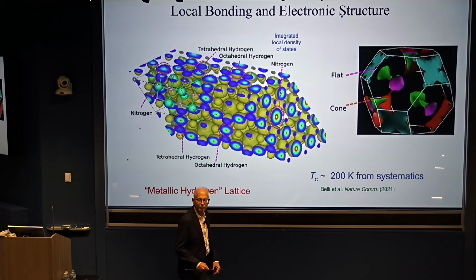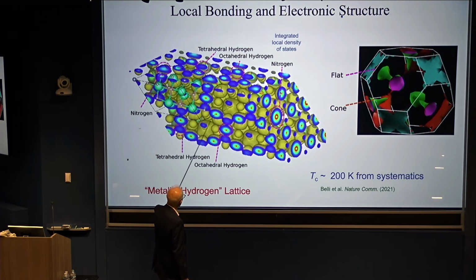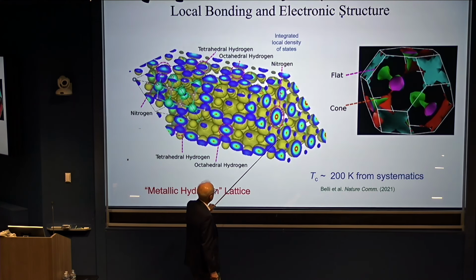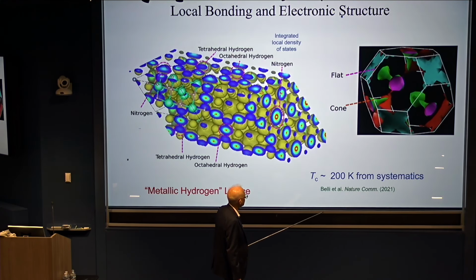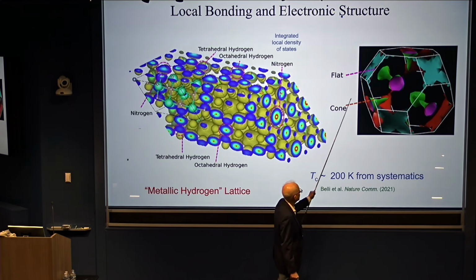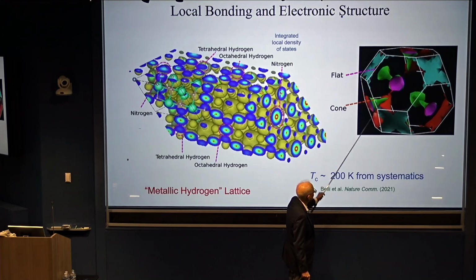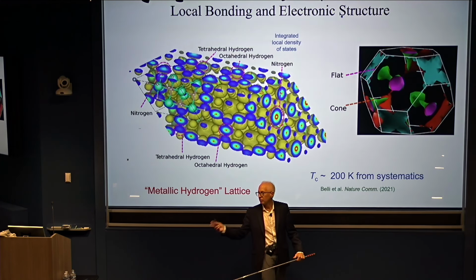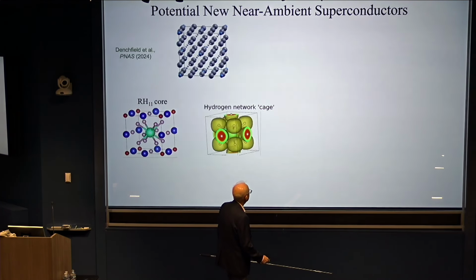If you look in real space, which is something more appealing to chemists, here we have a picture of what's called the integrated local density of states. And what you find here are the hydrogens, and so you have embedded inside this structure, even though it has fewer hydrogens, sort of like an embedded lattice structure of hydrogen. So it does have a metallic hydrogen lattice or cage structure, and if you can use systematics to estimate the TC, that's consistent. Here is the Brillouin zone, so for those of you who are interested in topological materials, it has flat bands and Dirac cones and so on. So it's really quite an intriguing material apart from its potential room temperature superconductivity.